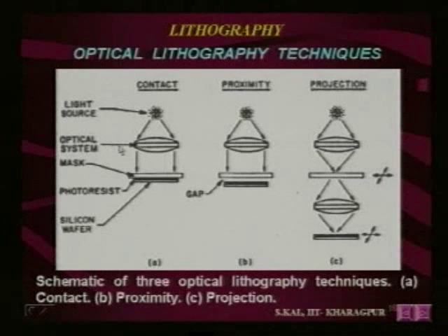And one problem of this contact lithography is that if there is any dust particle either on the mask plate or on the photoresist film, then during exposure in the contact mode, if I move it, the dust particle will make some scratch on the mask plate as well as the photoresist coated wafer. As a result, in a contact lithography technique, we have seen the life of the mask is limited, because after several uses you cannot avoid scratches.